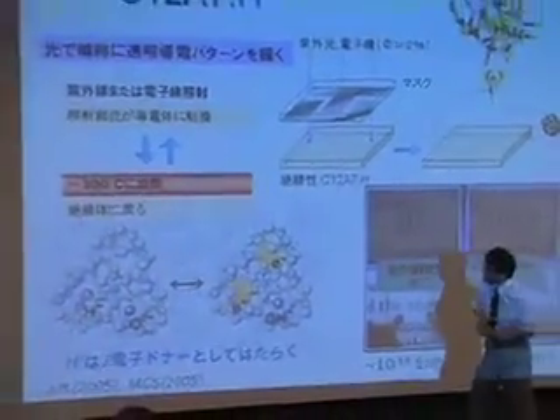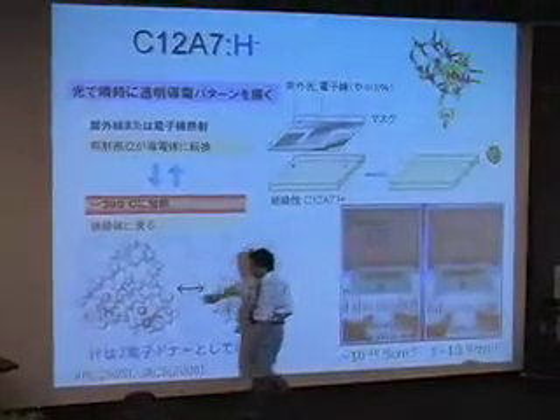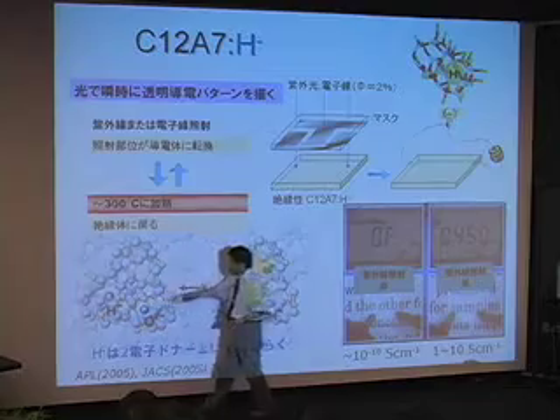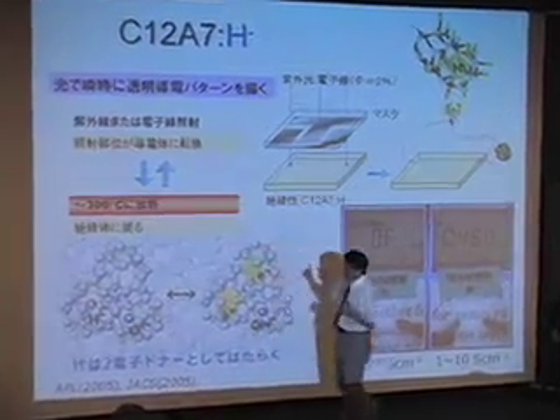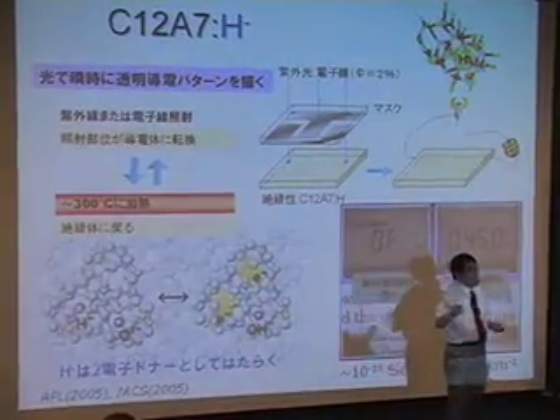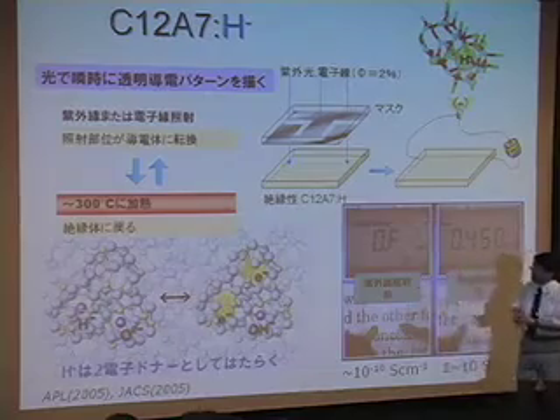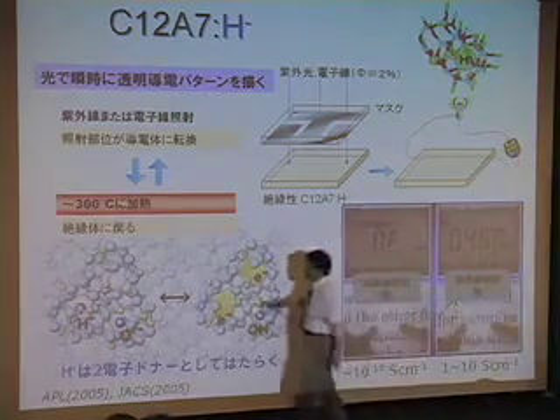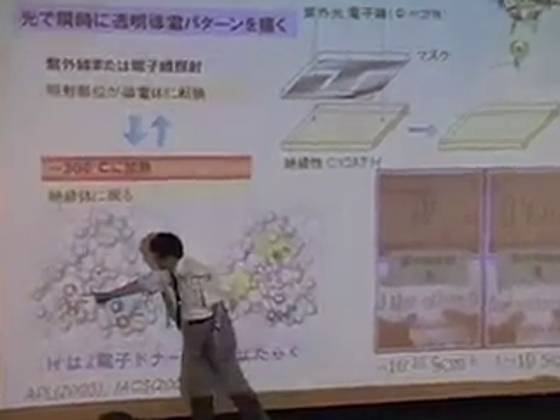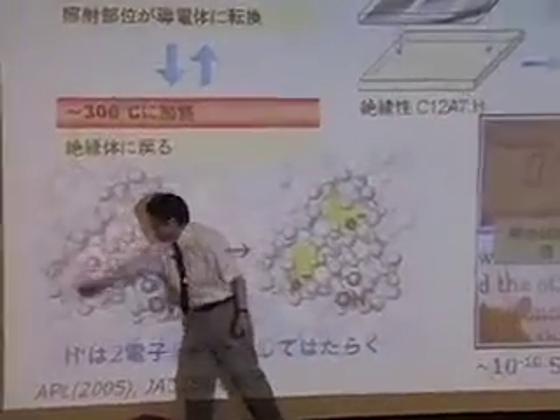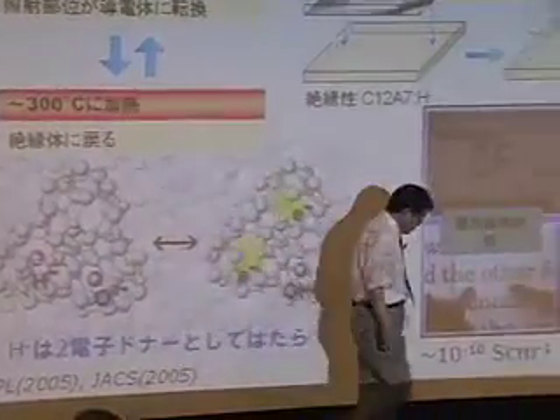So we found that when the sample was heated in a hydrogen atmosphere, H minus is incorporated, substituting the O double minus ion. Because hydrogen is stabilized, H minus is stabilized by the positive charge of the cage.